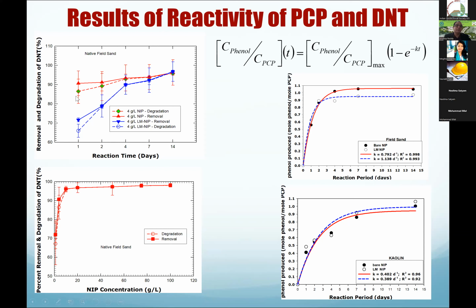So nano iron particles, bare nano iron particles are very reactive. So you have very high reactivity. Most of it gets degraded, right? So 90% gets degraded. But when you add lactate amendment, the reactivity goes down because of covering the surfaces of the nano iron particles.